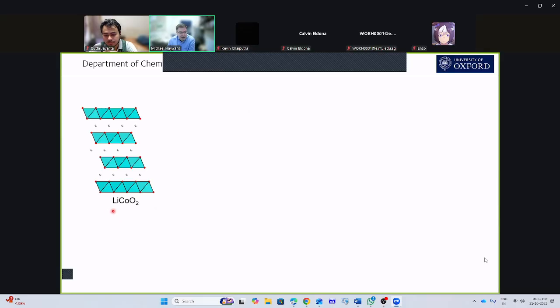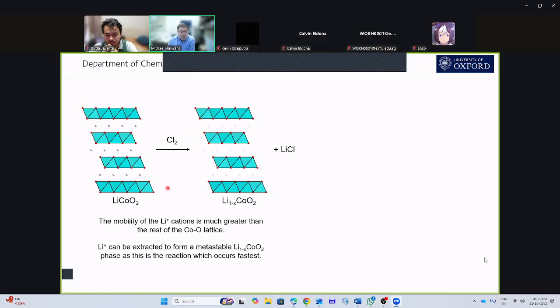So this lithium cobalt oxide should be familiar to most people. Actually, it was first used in a lithium-ion battery here in Oxford, about 10 meters from where I'm currently sat. John Goodenough used this for the first time in a lithium-ion battery system. And what you can see in this system is if I apply an oxidant, or if I do this electrochemically, I can extract lithium from the lithium cobalt oxide framework without changing the rest of the compound. And the reason I can deintercalate lithium from lithium cobalt oxide is that the lithium ions are much more mobile in the framework than the cobalt or oxide ions are.